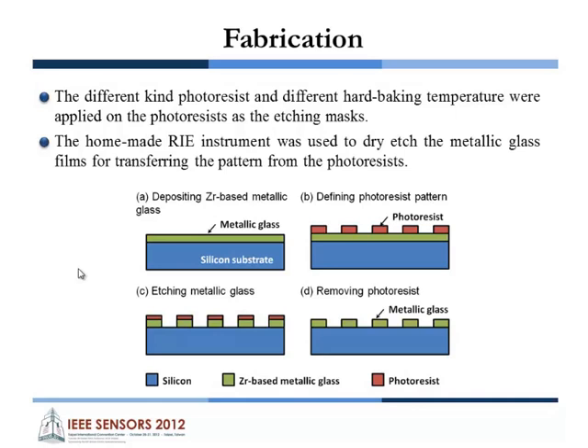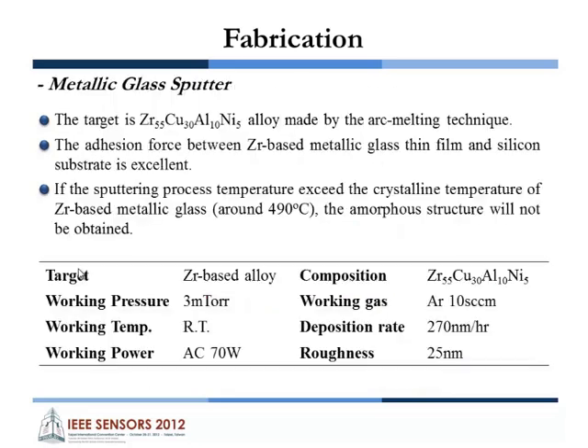Firstly, the metallic glass was sputtered on the silicon substrate, and then two kinds of photoresist were used to define the pattern on the metallic glass surface. And then we use a homemade RIE instrument to dry etch the metallic glass, and finally remove the photoresist. I will introduce more detail.